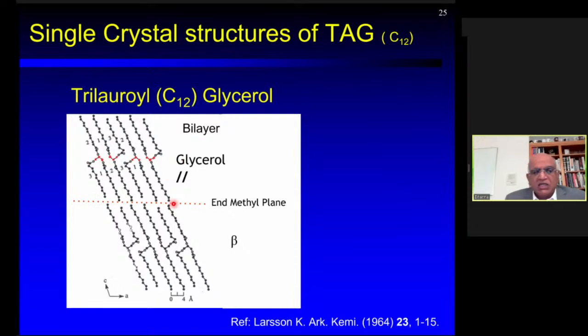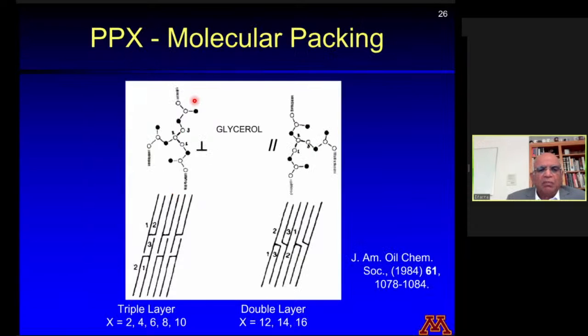With that understanding, let us examine the homologous series of compounds that we synthesized, the PPX. How they pack is shown here. This homologous series of compounds pack in 2 different modes in their most stable crystal form, in a trilayer structure as well as in a bilayer structure. When the acyl chain is shorter, 10 carbons, the short chains segregate and form a middle layer, forming a 3-layer structure interposed by 2 palmitoyl chains and the shorter chains in the middle. But when the 3 acyl chain is a little bit longer, closer to 16, they pack like a triacylglycerol in a bilayer structure, where 1 and 3 chains are together.